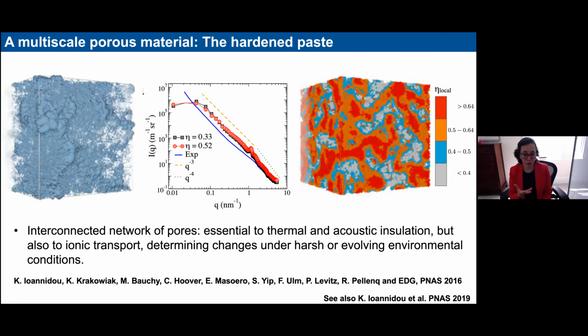The presence of these pores and the connectivity of these pores is very important for the interaction of the material with the environment and with different degrees of humidity and different types of environmental conditions that can evolve. So identifying this pore network is extremely important for understanding the durability and the resilience of the material in the infrastructure. On the right, you can see this structure, which has been colored in terms of the local density. You can see that the material is very dense, with parts of the structure that are extremely densely packed, but it's also very heterogeneous.